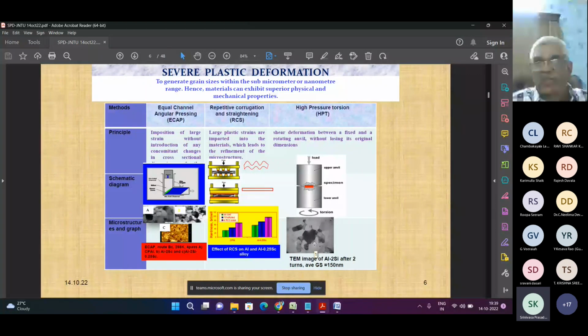The third and most important process is called high pressure torsion. Here, what is happening is shear deformation between a fixed and a rotating anvil without losing the original dimensions. If you can see in the center, the specimen is kept, something like 10 diameter by 1 thickness. When you apply some load and rotate from the bottom, I cannot show how it will rotate in the PDF, but you can see the TEM image, the grain size has become 150 nanometers. That is after 2 turns, particularly when we did it for aluminum 2 silicon alloy, the average grain size reduced to 150 nanometers. One micron is 1000 nanometers, so it has reduced to 150 nanometers.